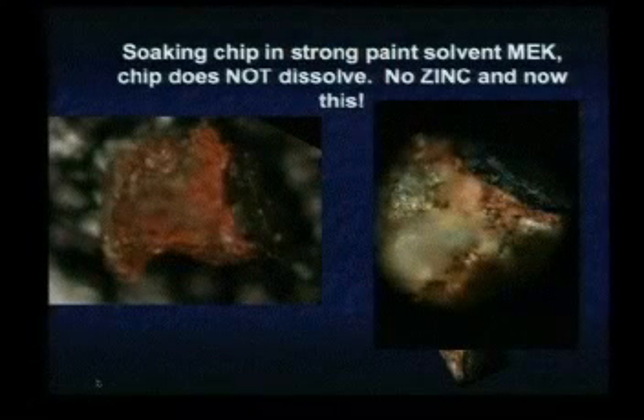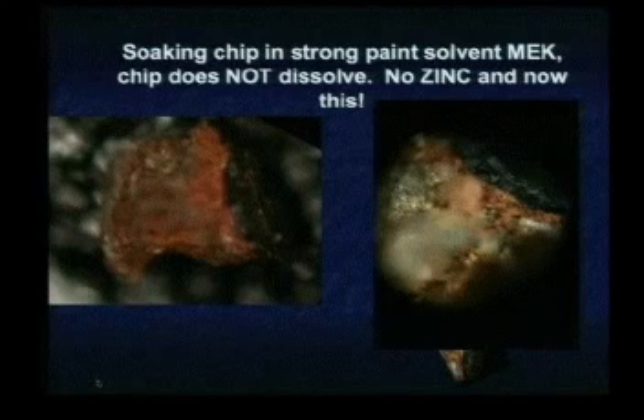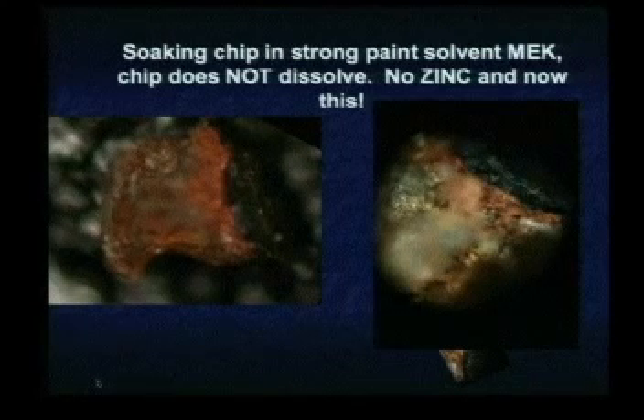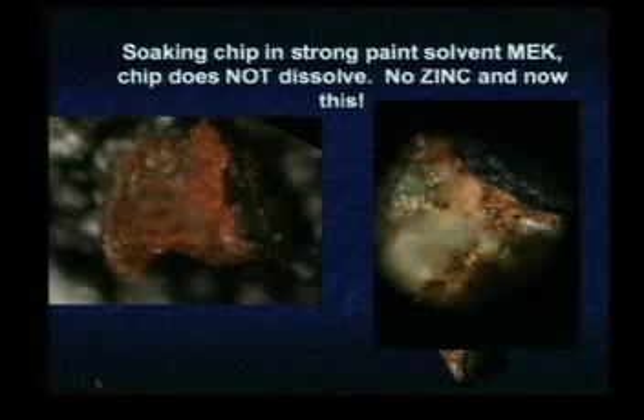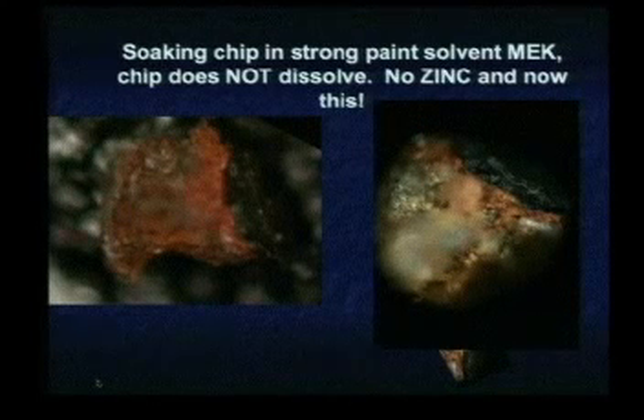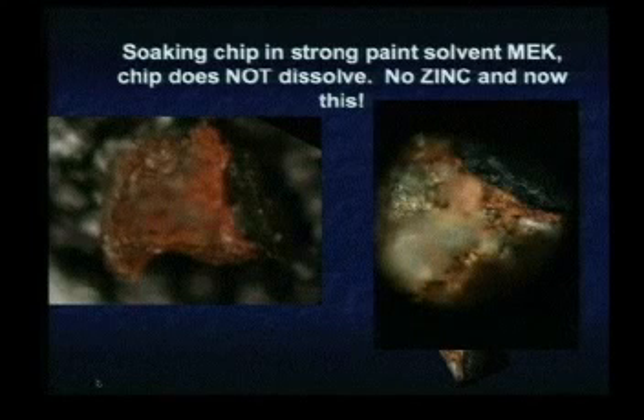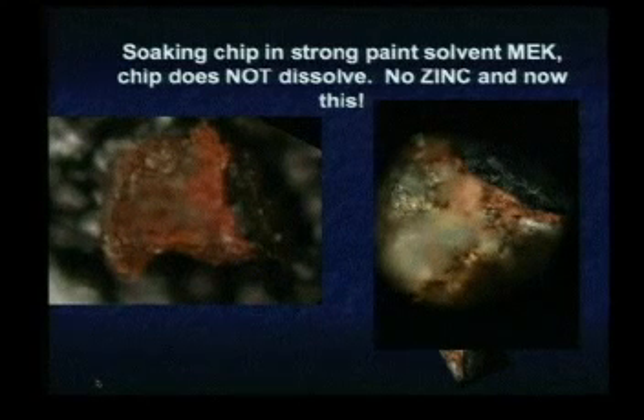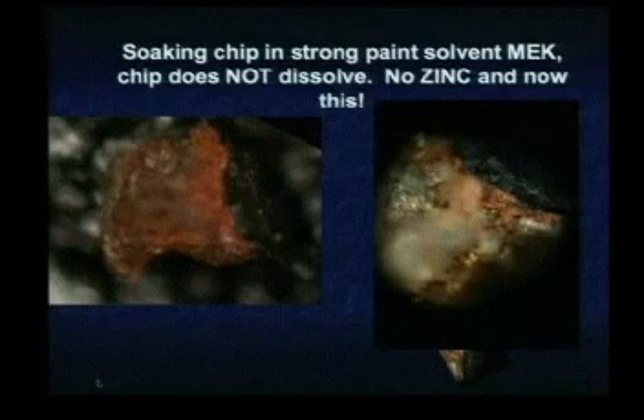So I soaked some chips in paint solvent, working with Dr. Fair. This was one of the early tests we did: the chip does not dissolve. Paint, which we also soaked, I bought the solvent, methyl ethyl ketone, at a hardware store, it's a paint solvent. I put chips of paint in there and they dissolved. Certainly the paint got flimsy, and then you see dissolution. But these chips did not dissolve at all. And there's no zinc, and now this, it's just not paint.